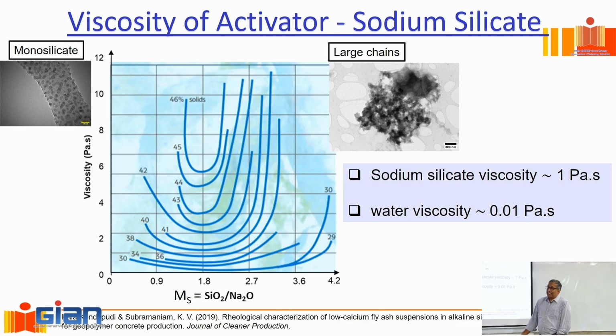So, is there a one size fits all for alkali activated binders? No. Understand the rheology of the binder paste. How much silica content do you have in your solution? What is the MS, this ratio of the solution? And what is the solids to activating solution mass ratio? And understand that adding more silica will make the solution more viscous, and there's a greater likelihood of it becoming a Maxwell flow. If it becomes a Maxwell flow, good luck with the structuration. It's not going to structure.